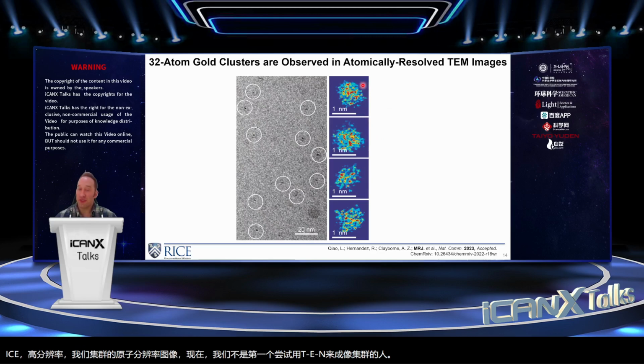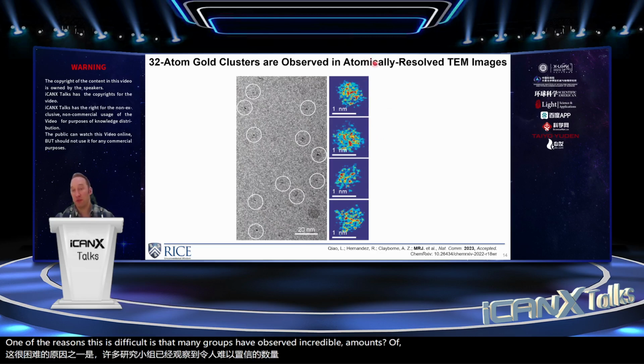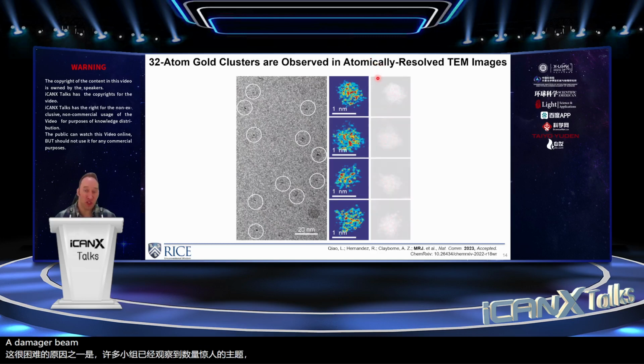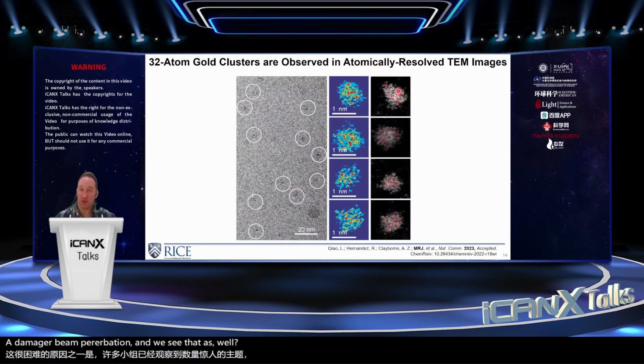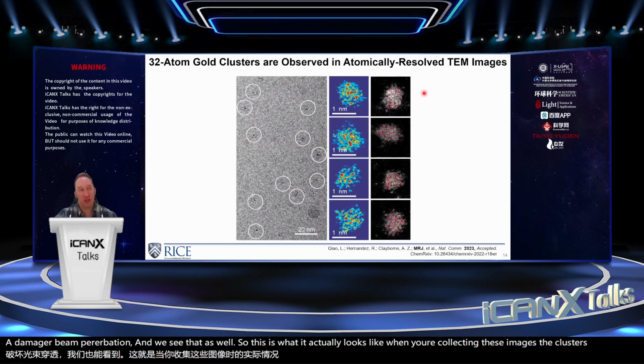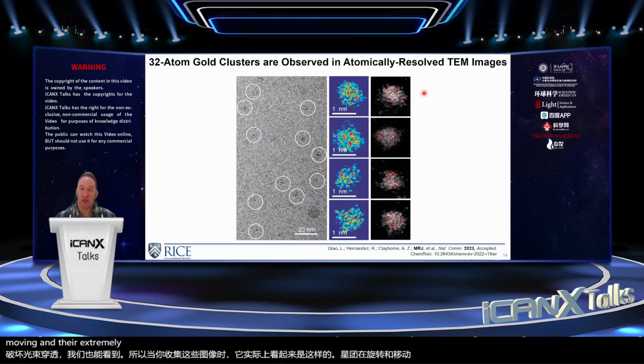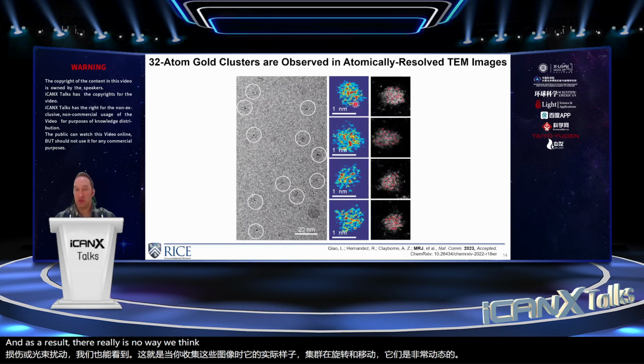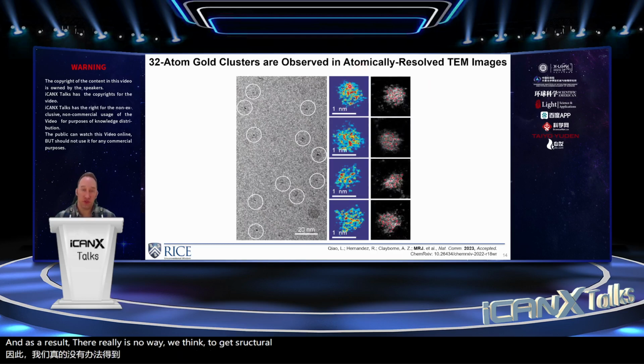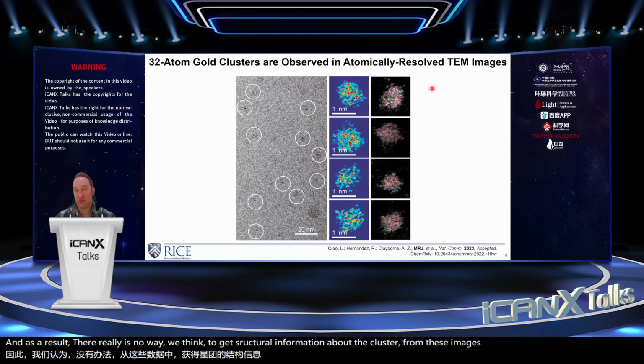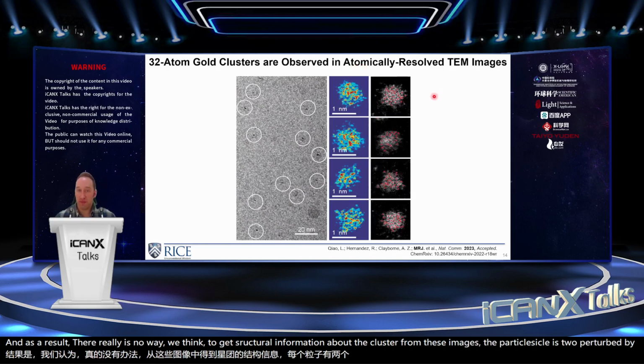One of the reasons this is difficult is that many groups have observed incredible amounts of beam damage or beam perturbation, and we see that as well. So this is what it actually looks like when you're collecting these images. The clusters are rotating and moving, and they're extremely dynamic. As a result, there really is no way, we think, to get structural information about the cluster from these images. The particle is too perturbed by the beam.